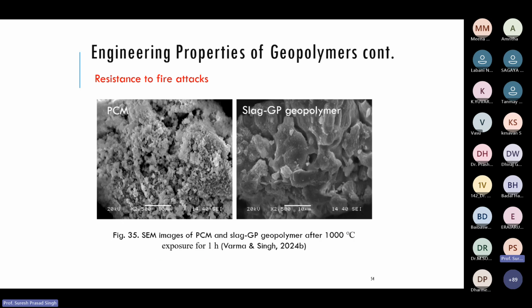This is the structure after exposure. This is the disintegrated structure, and here the intact gels have their hydration products, strong products. It is not disintegrated, though it was subjected to a very high temperature of 1000 degrees Celsius for 1 hour.